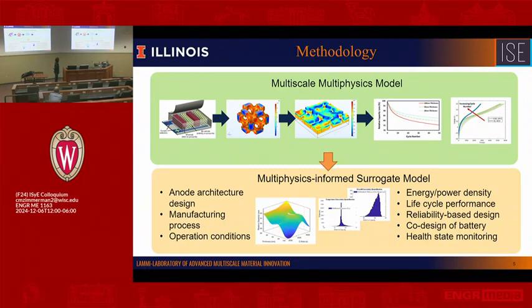lithiation or delithiation process. But how can we identify? Although current studies have demonstrated it's quite useful for mitigating the stress induced by volume change during the use of silicon anodes, how can we quantify such effects and use such knowledge to assist in the design of the battery? It still needs a lot of work. Besides that, if we rely purely on experimental study, that's quite expensive. We would have to do repetitive experiments and collect a lot of data from experiments to facilitate the design process. That's not very feasible, to rely solely on experimental testing.